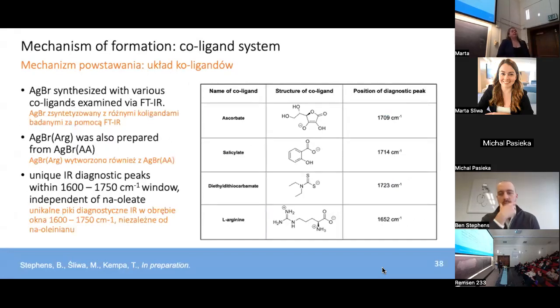We also hypothesized that these co-ligands may act as a defect point in that ligand shell. So not only are they existing as a stabilizer, but they might be gating the association of the L-arginine, which we previously discussed was very important and necessary to the formation of our dimers, to the silver bromide surface. And to test this out, we turned to Fourier transform infrared spectroscopy, or FTIR.